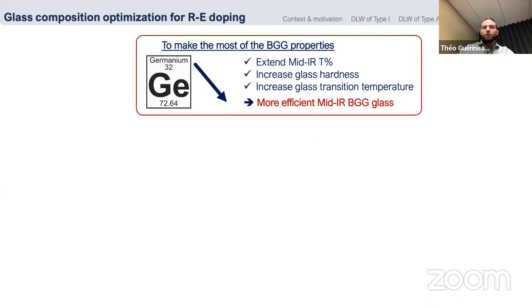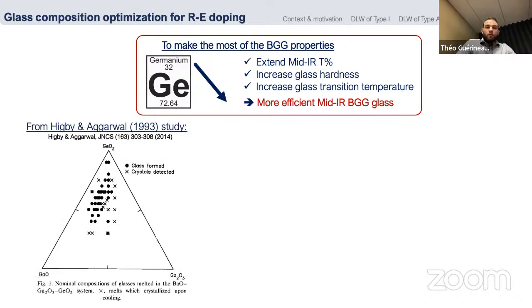So if we want to make the most of BGG properties, to extend the mid-infrared transmission, and to increase the glass hardness and glass transition temperature, we have to reduce somehow the germanium content. What has been published by Higby and Aggarwal in 1993, here is their ternary diagram, as I showed you also earlier. So we selected the BGG composition with the lowest germanium content, and we fixed the concentration of barium, and then we increased the gallium content just to see how we can stabilize the glasses to the fiber drawing process.